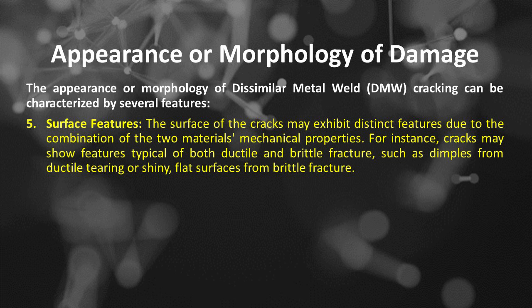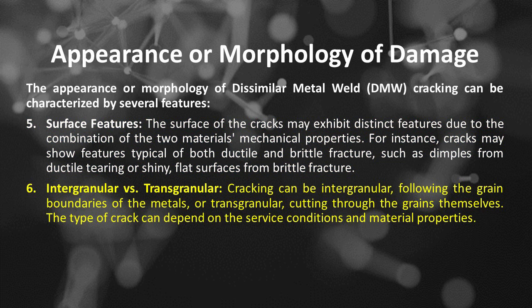Number 5 is surface features. The surface of the cracks may exhibit distinct features due to the combination of the two materials' mechanical properties. For instance, cracks may show features typical of both ductile and brittle fracture, such as dimples from ductile tearing or shiny, flat surfaces from brittle fracture. Number 6 is intergranular versus transgranular. Cracking can be intergranular, following the grain boundaries of the metals, or transgranular, cutting through the grains themselves. The type of crack can depend on the service conditions and material properties.